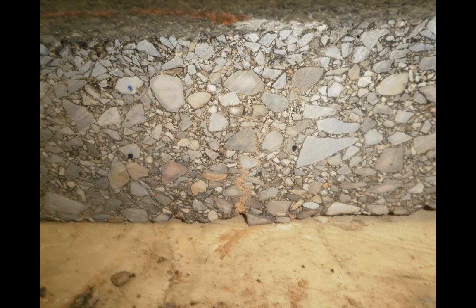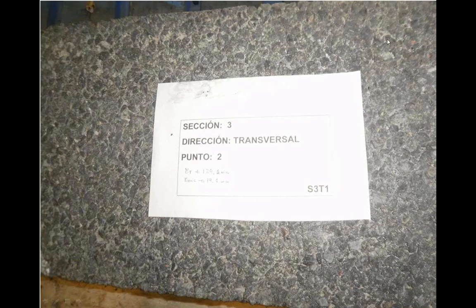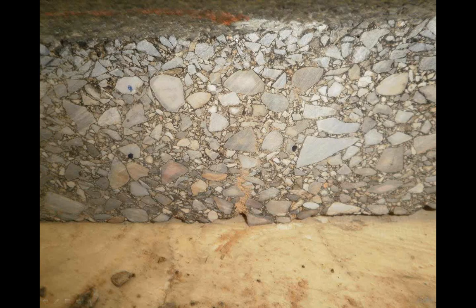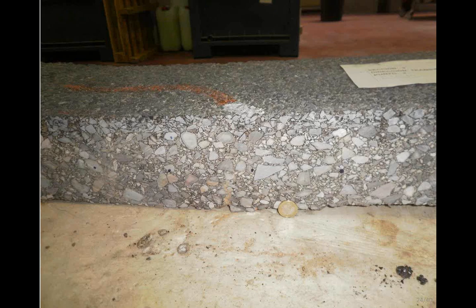We have to say that the material here is a conventional asphalt concrete. In fact, this is a low quality asphalt concrete. For the wearing layer we were using an open graded mixture. This mixture that you can see here is an open graded mixture, and it was very difficult to see cracking through this wearing course. But for sure most of the cracks were bottom-up cracks. You can see here another crack. Here you see another crack.